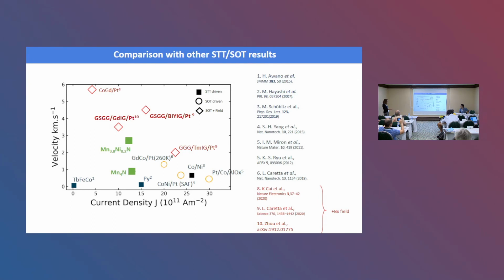Then we have all these results here, which are garnets, so you can see these huge velocities for the magnetic garnets. These are spin-orbit torque driven domain wall speeds, but in this system the DMI is not strong enough to have Néel walls, and so an in-plane field was applied in order to move the domain walls. So these are all with in-plane magnetic field applied on top of the current.